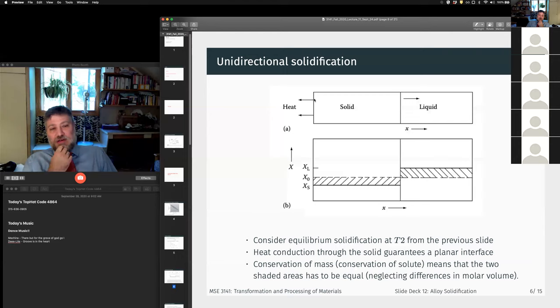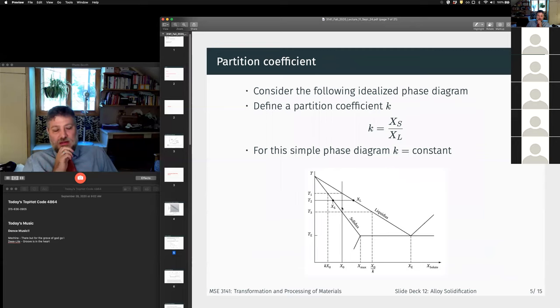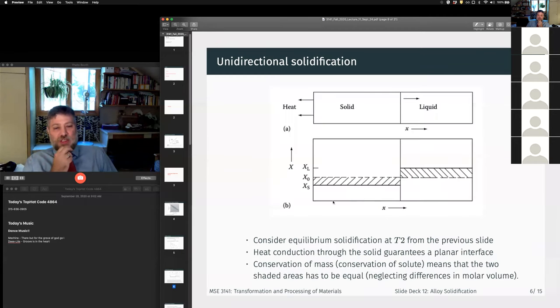So let's consider unidirectional solidification. And here we're going to be considering the case where we're conducting heat out of the solid. So if we're conducting heat through the solid, it means this interface is going to stay planar. We also know that as we freeze, if we're in this region here, at the beginning part here, the composition of the solid is less than our overall composition and less than the composition of the liquid. So if we're doing this very slowly and allowing the composition to equilibrate, it means that the composition of our solid is XS, the composition of our liquid is XL, and the composition overall is given by X naught.